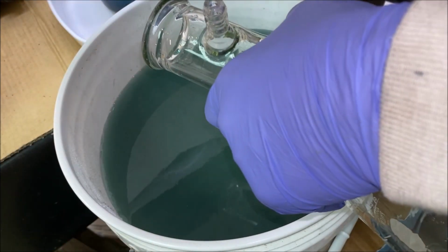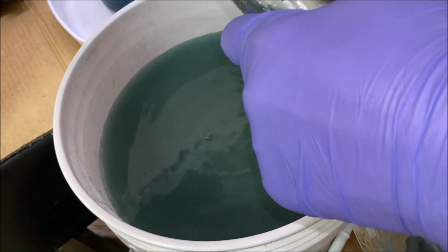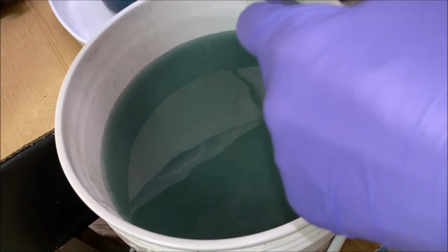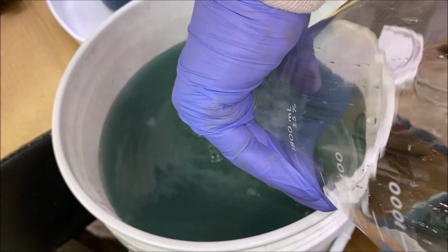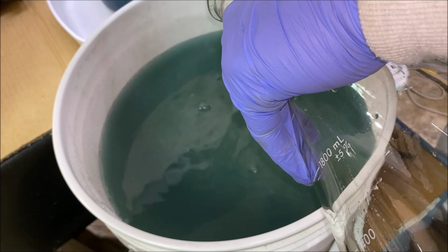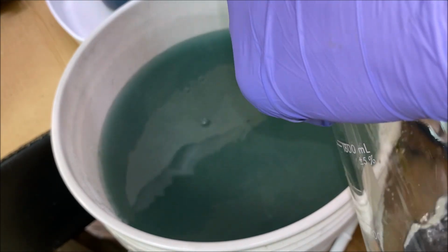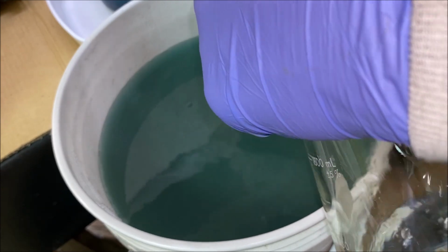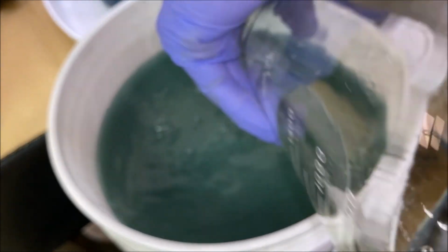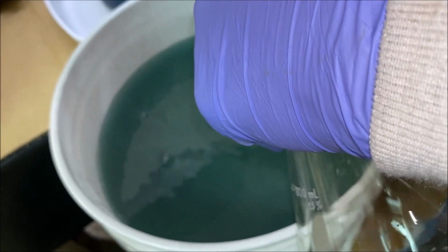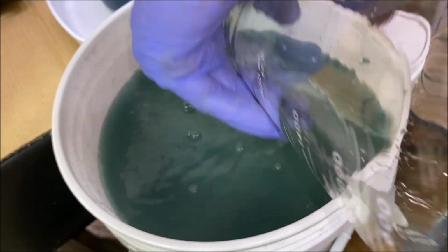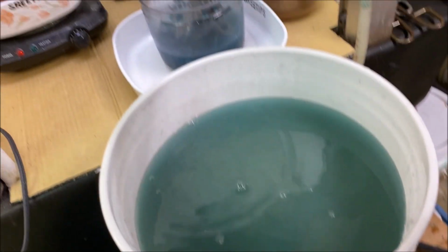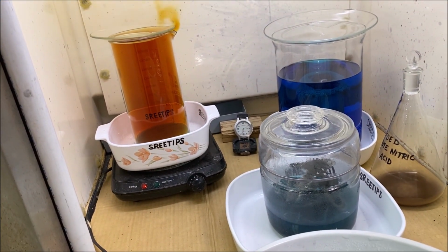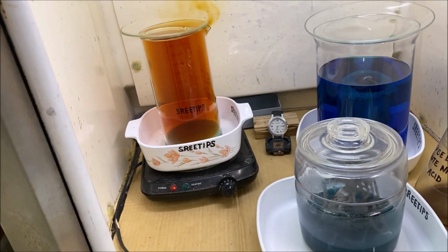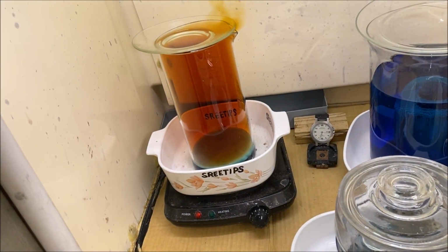So as you can see, this is where the silver comes from that I run through my silver cell. I use sterling silver to refine the gold. I alloy the scrap gold with sterling silver. And the reason I do that is so that the nitric acid will be able to penetrate and pull the silver and the base metals back out. And when I get done with that reaction back there, that red one, I'll have nearly pure gold left in the bottom of that beaker.